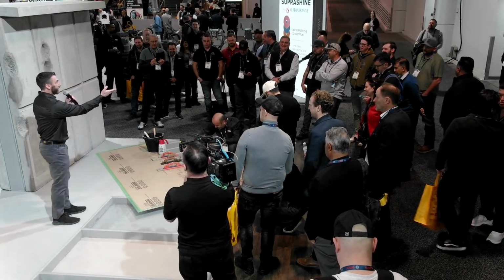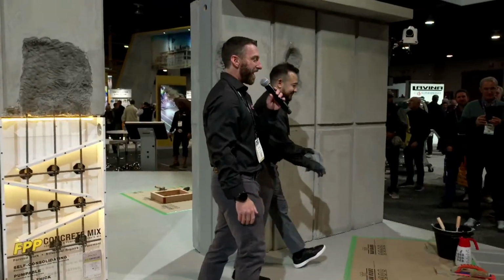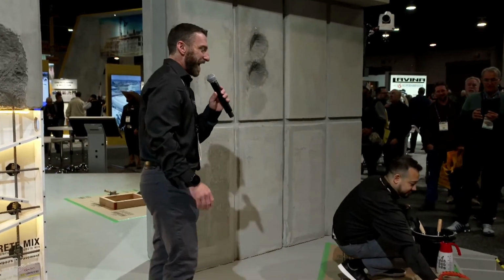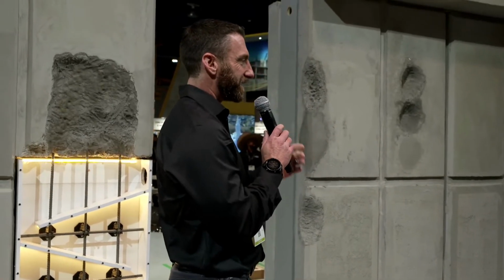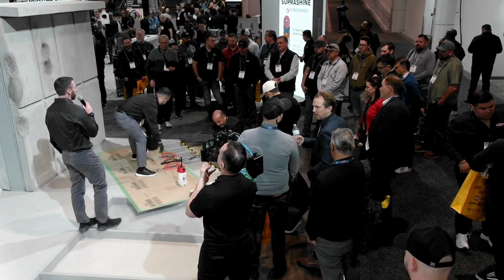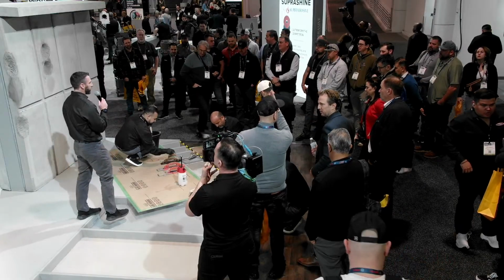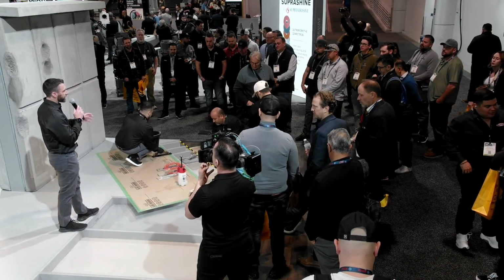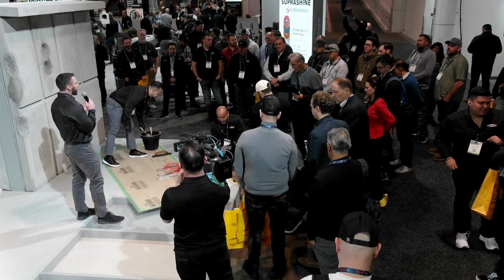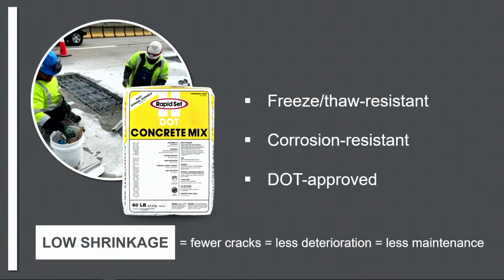Well, you, sir, will be glad to know this is formulated for high freeze-thaw durability, and it also has an integral corrosion inhibitor. So we have independent testing by ASTM C1202 that measures chloride ion permeability. And what that test shows is that the chloride ions have a very low permeability, which means salts and water have a very difficult time making it through this product to attack the embedded rebar. And that's because it contains integral corrosion inhibitor.